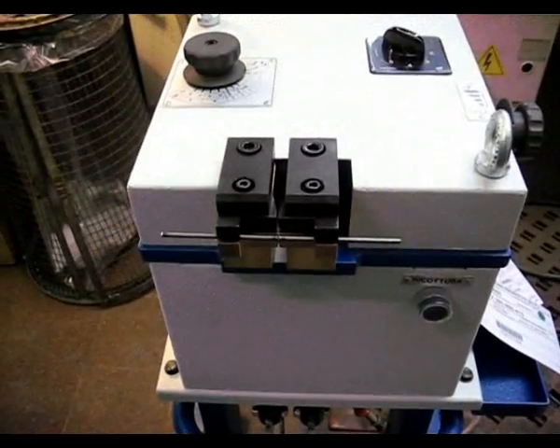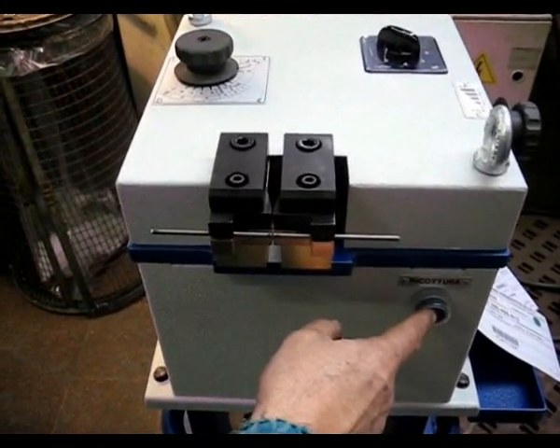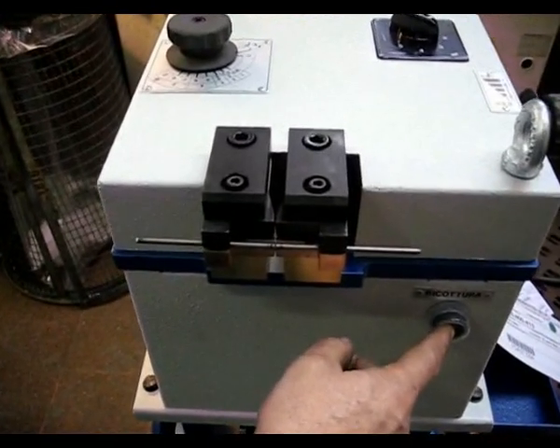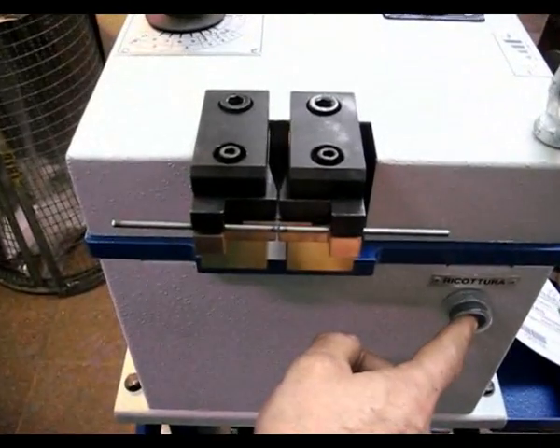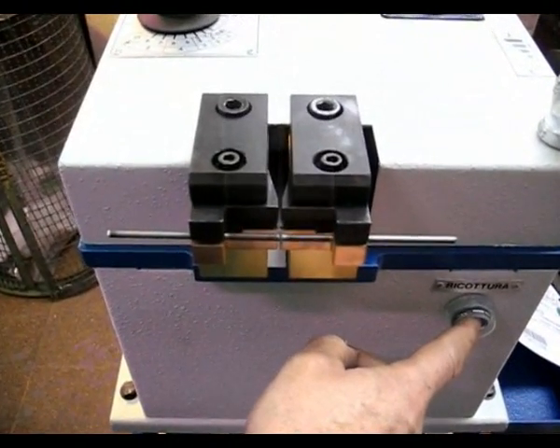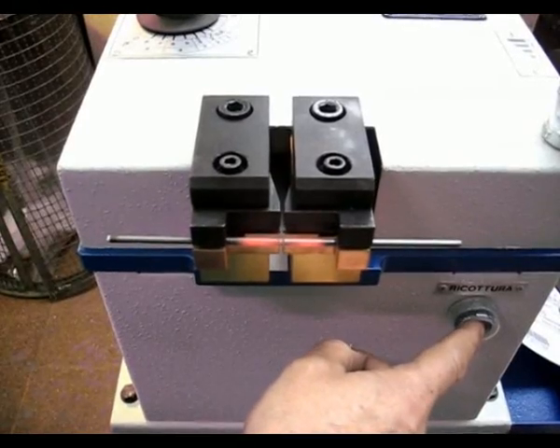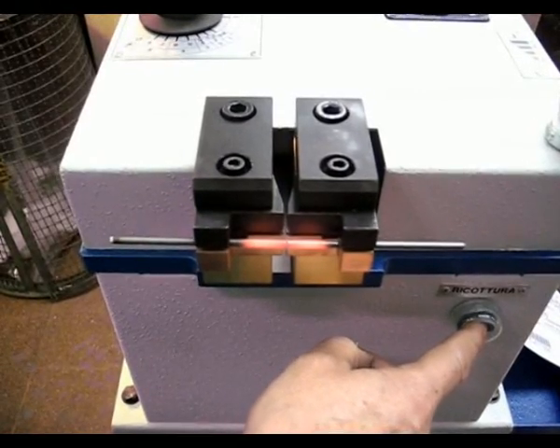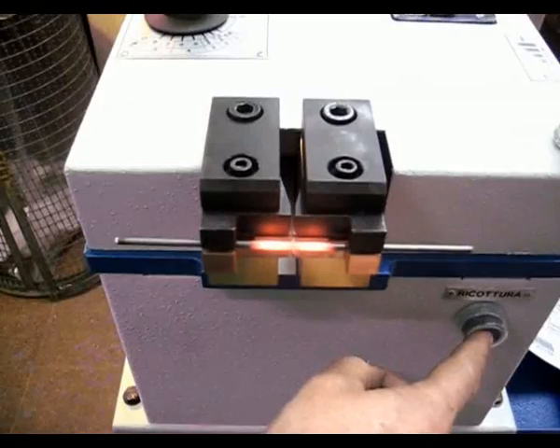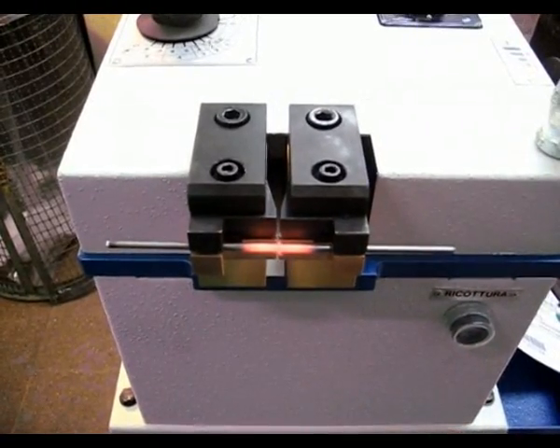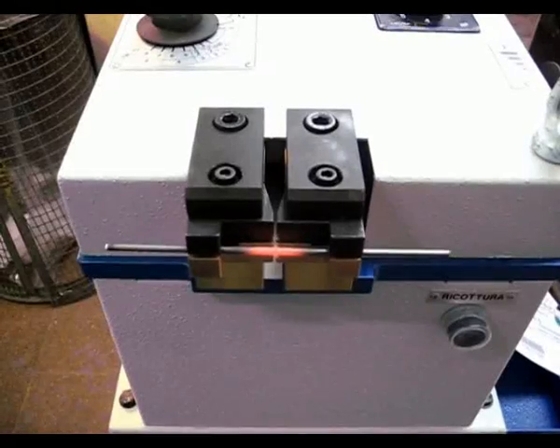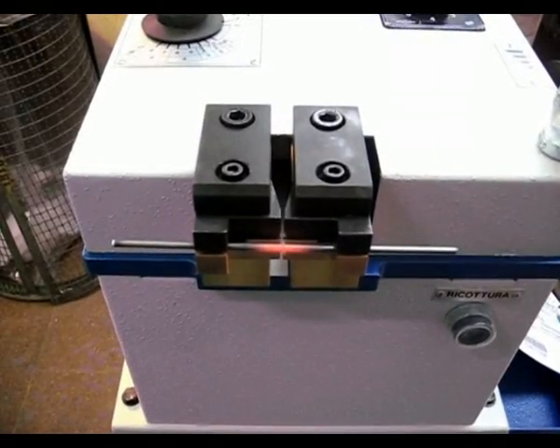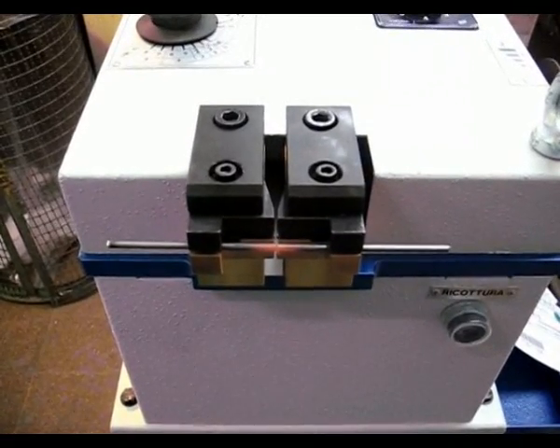Keep pressing and release the annealing button a few times, as long as the wire becomes red as a cherry. At this point let the wire cool down.